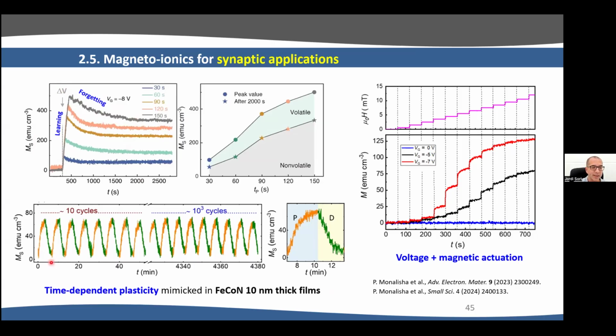Of course, we can induce cycles. We can do potentiation depression cycles up to more than 1,000. And here on the right, what I want to show is that this multi-level memory actually in Magneto-Ionics can be controlled with voltage, but it can also be controlled with magnetic field. So here you can see 3 curves for different voltages, and here we are changing the magnetic field. So this is something that memristors cannot do. Memristors are materials that are typically used in neuromorphic computing. There you can change the amplitude or the synaptic weight just with voltage. Here you can play with 2 degrees of freedom, voltage and magnetic field, adding extra functionalities.